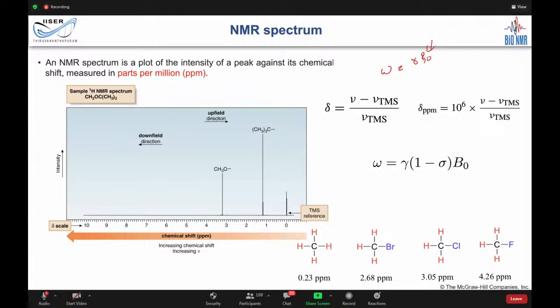So delta is defined as nu, the frequency of your interest, minus nu TMS, the frequency of your TMS signal, divided by nu TMS. Now nu TMS is in megahertz, so you have a 10 raised to 6 on the bottom. So you have to multiply by 10 raised to 6 to get the delta ppm value. This is the delta scale that we normally have for proton NMR, or hydrogen nuclear NMR. It goes from 0 to 10 generally.